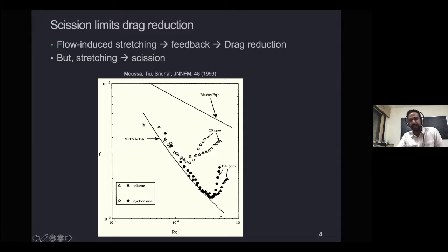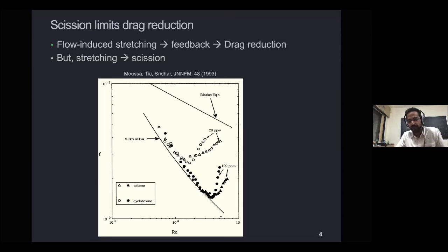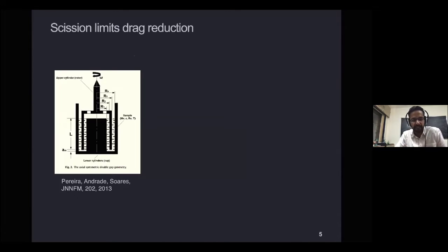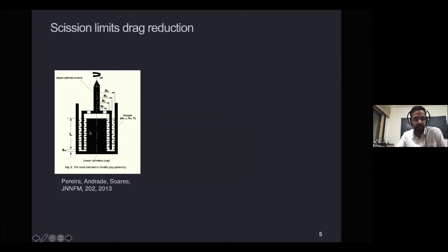This loss is delayed at higher concentrations but eventually you see the same behavior. This really happens because the polymers start breaking up beyond a certain Reynolds number — if a sufficient number of them break up, there's nothing left to stretch and react back on the flow, and you lose drag reduction. This is a flow-through experiment with a fixed residence time, but a different sort of experiment lets you actually track how polymers break up in time.